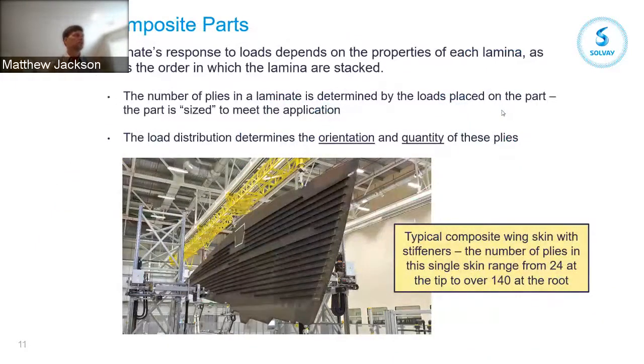This just gives an example of why we would want a layup with different directions. Typically, when we go to these composite structures, we can get away from what we call the quasi-isotropic layup or a balanced layup. Here is an example of a composite wing skin. You can see there are stiffeners going from the back of the image to the front. The thickness of the composite structure is a lot thicker at the root than at the tip. At the root, we have around 140 plies, and at the tip, we have around 24.